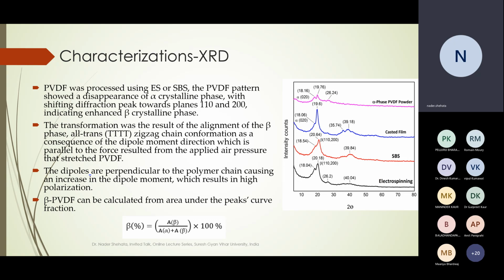However, if you prepare the PVDF using electrospinning or solution blow spinning, then most likely you will find that the previously shown patterns or peaks related to the alpha phase start to disappear, and other peaks related to the beta crystalline phase will be shown, which is related to the all-trans formation of the monomer chains. Consequently, this one, which is called the beta phase, is the most needed one to form the piezoelectric nanofibers, according to the orientation of the dipole moments parallel to each other, and then it would be highly responsive to any applied forces on the PVDF nanofiber.